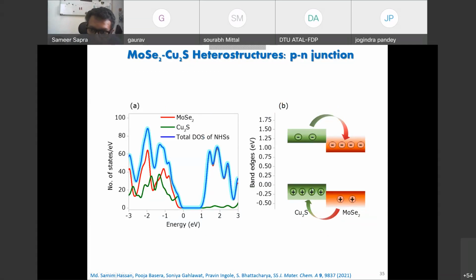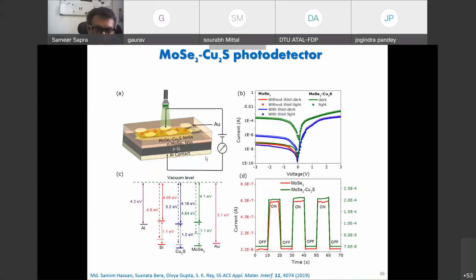This is the valence band for cuprous sulfide, and this is the valence band for MoSe2, and those are the conduction bands. So you see that the conduction band is lower in energy, and so the electrons go to MoSe2, and the valence band is higher in energy, and the holes go to cuprous sulfide. So there's a natural separation of electrons and holes in these materials. So if there's a natural separation, then I could use it for a number of applications. I could use it for photovoltaics, I could use it for photocatalysis, the simplest one, photoconductivity, and one could make a photoconductive device over here.